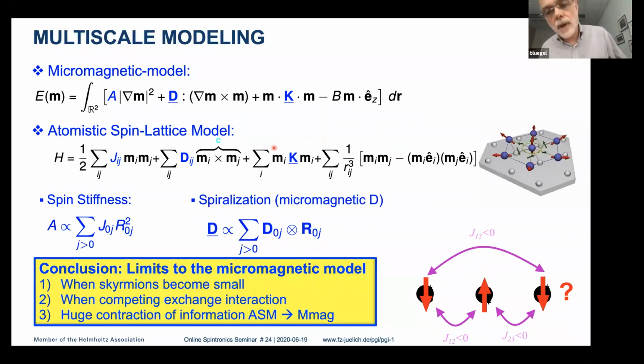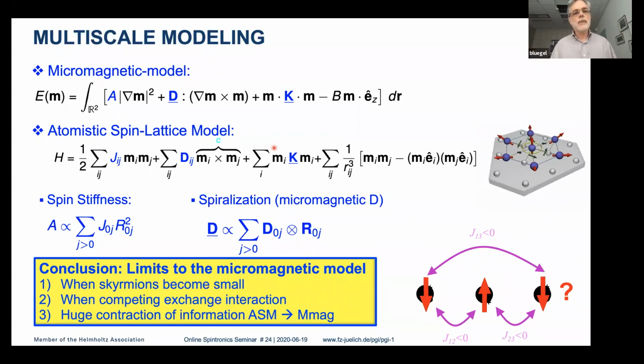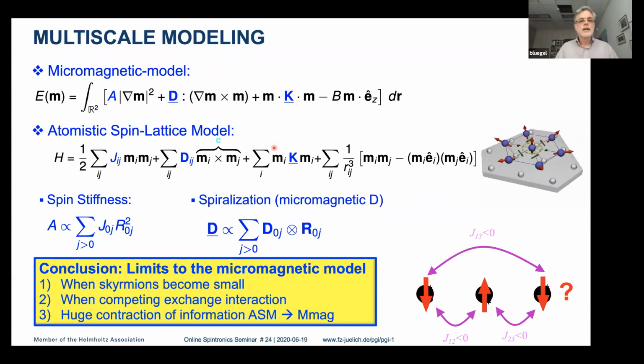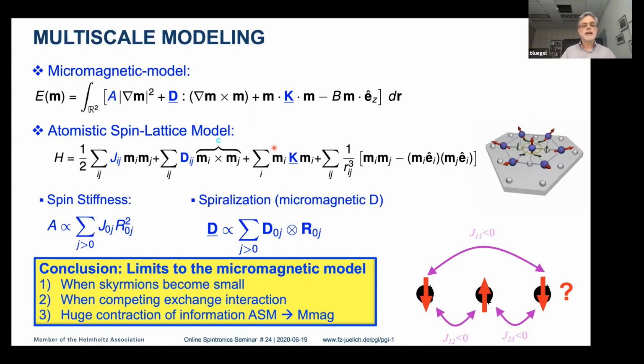And I would like to make one important remark here. Of course, micromagnetism has its great values. But I also would like to say it is limited if the skyrmions become small. It has some problems with competing interactions. And you should also realize an important thing. There is a relation between this parameter A and the many long-range interactions J, which is basically a huge contraction. So you have all these microscopic parameters from the nearest neighbor, next nearest neighbor, and so on in all possible directions. At the end, you contract everything to an A. And the same happens with the spiralization, where you calculate the Dzyaloshinskii-Moriya interaction and contract it to one number for one tensor.